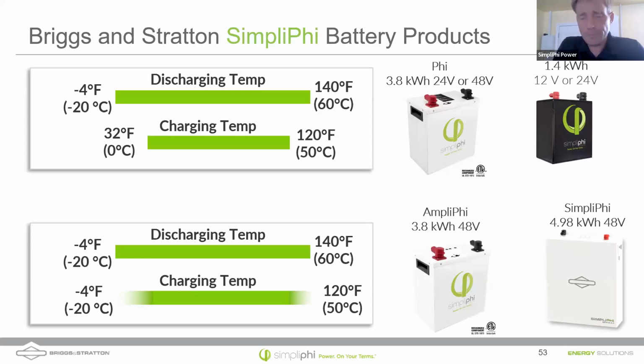So let me get to this slide that Daniel was asking about earlier, that somebody had asked about earlier, and Daniel was referring to. So for our non-communicating batteries, the PHI batteries, we're really limited in our temperature range to 0. We can't charge below 0, and that's because the lithium has a really hard time getting into the graphite. And so it can build up and even form what are known as dendrites or branches. It's basically solid lithium deposits that can damage the cells over time. So it's important, if you have non-communicating batteries, that you do something if you're in a cold environment to make sure that the charging equipment doesn't try to push charge in cold temperatures. For the communicating batteries with appropriate equipment, the communicating batteries can dictate how fast they want to be charged, and they monitor internal temperatures in various places within the battery cells.